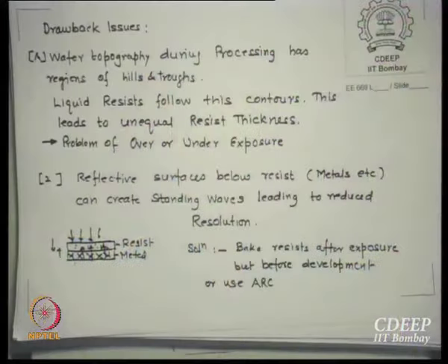If it is like total internal reflection, then most of the beam may go out, but I want most of the beam to get in. So I must adjust both the thickness D as well as the density or refractive index there, so that most of the light is absorbed and not reflected. Is that clear to you? This is essentially what is tried in the baking system. We will come back to it tomorrow.